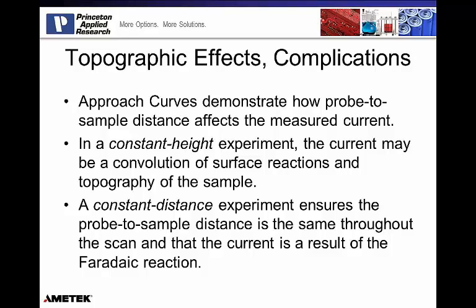Now, if your sample is polished flat and not tilted, the constant height experiment can make these measurements for you. But if you have more complex geometries, with curved samples or sensors that may have some topographic character to them, this is where we're going to need some way to measure constant distance, save that almost like a background file, and increment that probe in Z as it goes across the plane above the sample surface.